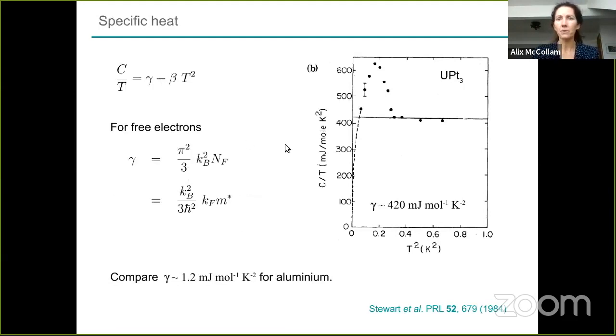Examples just to show you what it looks like experimentally and give you some numbers. So the specific heat, if you plot C over T and look for the gamma coefficient, this is uranium platinum 3, which is one of the very important heavy fermion materials, because it's one of the few that is a very good Fermi liquid, and the properties of the Fermi surface and the effective masses in the de Haas van Alphen effect and the specific heat all correspond to each other very nicely, which was good, that there was at least one material that did that, I think, in the early days of heavy fermion physics.